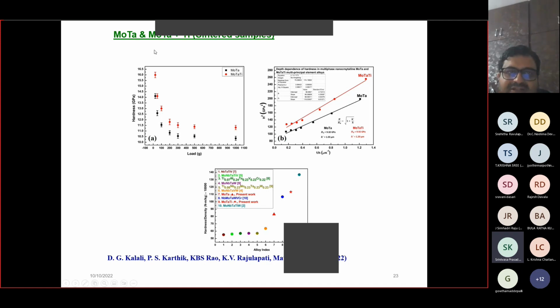And this variation of hardness with load, which is the indentation size effect, a very pronounced one that you have seen in this case also, is explained using geometrically necessary dislocations to account for the very high hardness at the beginning of your hardness measurement at low loads.